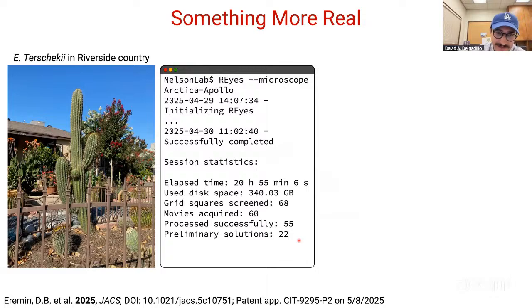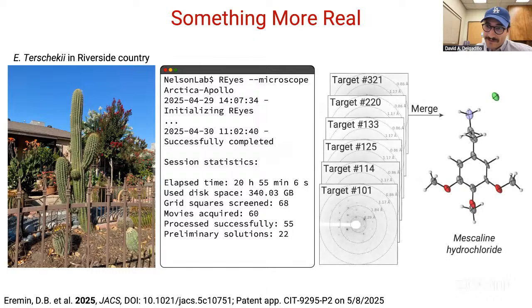And so earlier, Dmitry was showing how you can kind of get crystallographic data or even a structure from 9 grid squares. Here, when you have a whole heterogeneous mixture, it takes a little bit more time, but we went ahead and ran it anyways, and we were able to get structure mescaline hydrochloride. And for reasons unbeknownst to us, this was the only thing that we got from this sample. So don't ask me how it was extracted, but we went ahead and ran mass spec, and we were able to confirm that there were other natural products in there, but a majority of it was this mescaline hydrochloride.